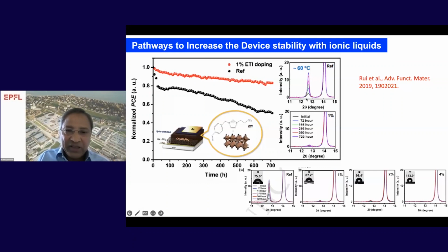If you see, in the reference sample, the formation of lead iodide is significantly dominant. In the presence of 1% ionic liquid, after 720 hours of heating at 60 degrees, you can see the absence of the formation of lead iodide peak. So this way you can increase the stability of the perovskite composition.